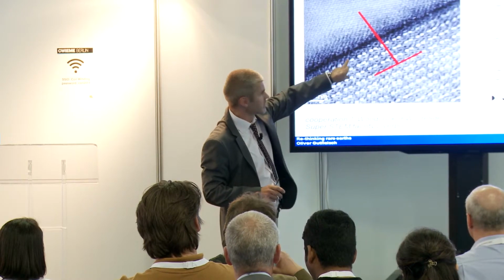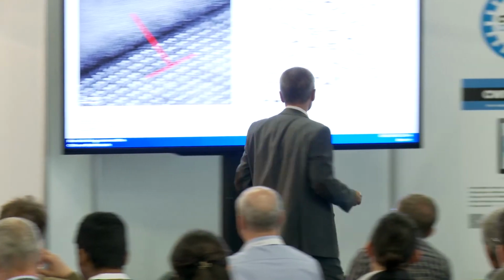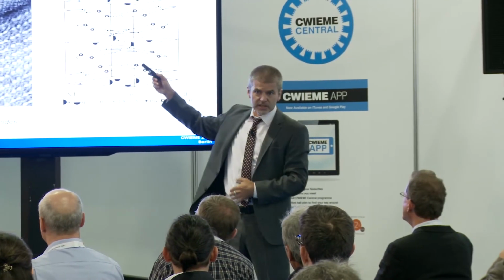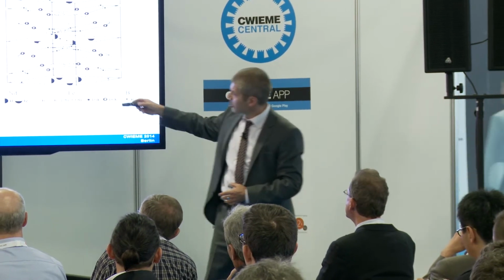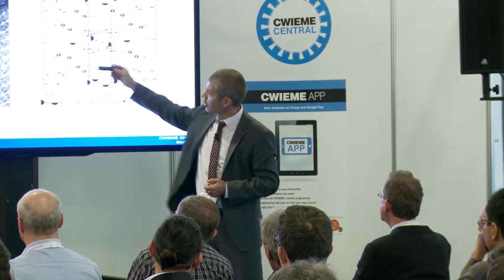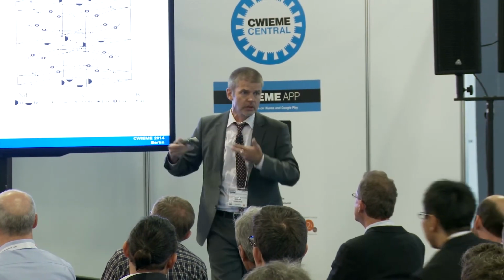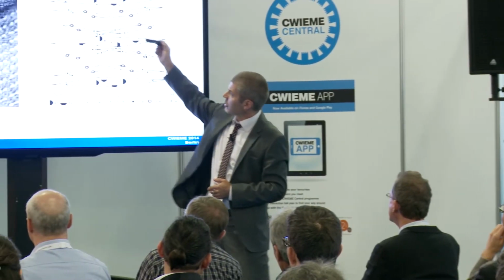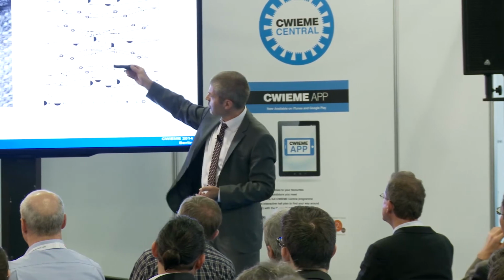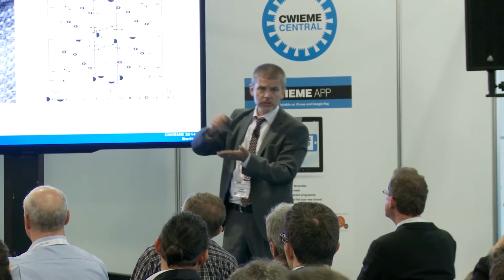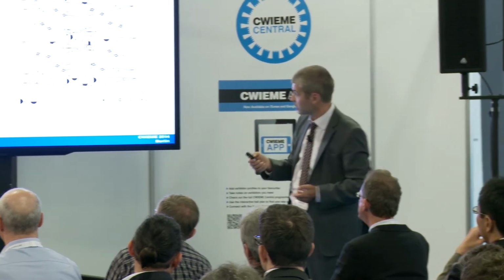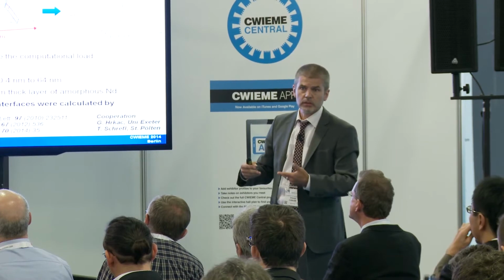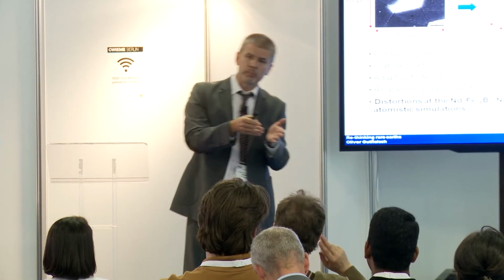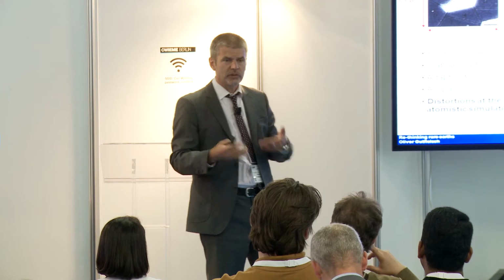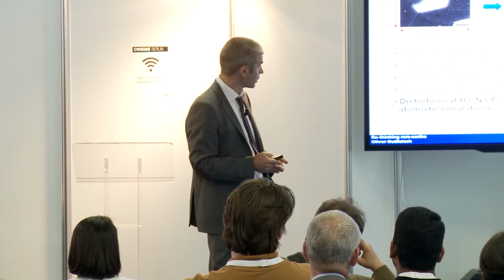And you can see here, hopefully, there are these little rings, and these are the rings out of the unit cell. That's why I say this structure is so close to perfection: we use little light rare earth, a lot of iron, cheap, abundant, high magnetization, and then another rare earth layer. So we have this coupling of high anisotropy with high magnetization, even on a unit cell basis. That is the beauty of this compound. And this multi-scale characterization is coupled to multi-scale modeling. On a computer we can replace one phase with the other and understand what we in principle should do to make these magnets better.